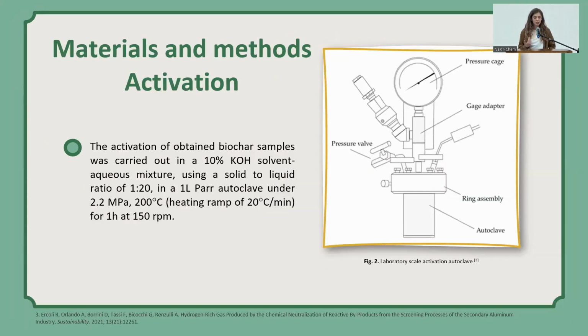The activation was carried out in a 1 liter autoclave with mechanical stirring, maintaining a constant temperature and pressure at 200 Celsius degrees and 2.2 megapascal. We used an aqueous solution of 10% potassium hydroxide for the activation, at a ratio of biochar to liquid of 1 to 20. The reaction took place for 1 hour at 200 Celsius degrees with a ramp of 20 Celsius degrees per minute.